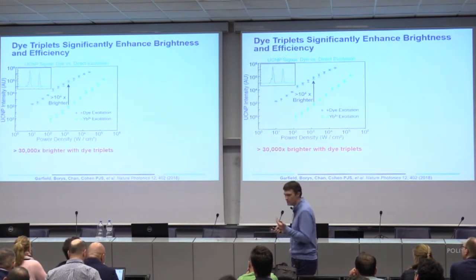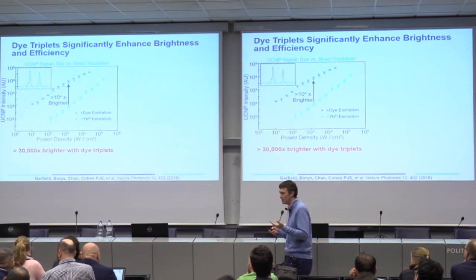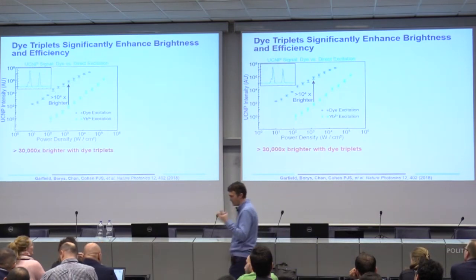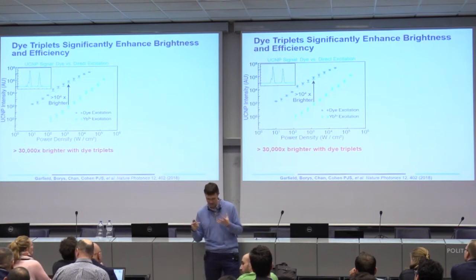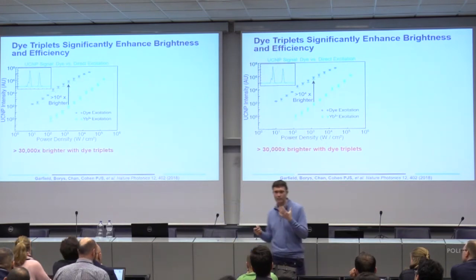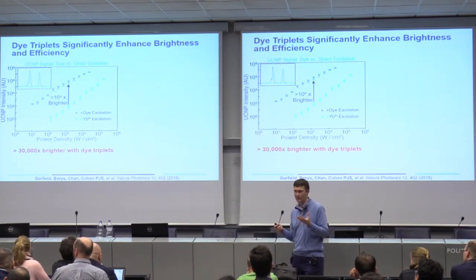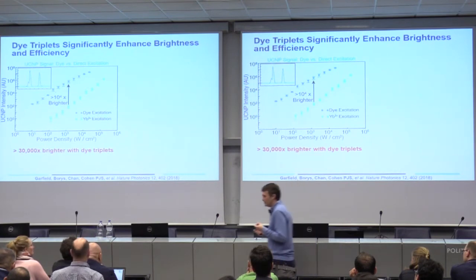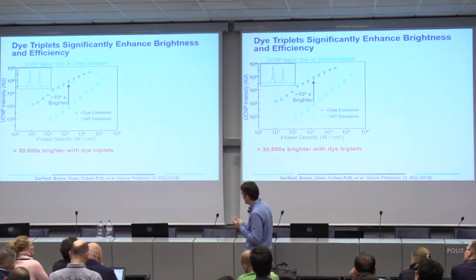And so what this means now is we put dyes on our molecule. We changed the composition a little bit so we could really take advantage of this triplet effect, this intersystem crossing. And now we have particles that are 30,000 times brighter than without the dyes. So this got us pretty excited. So yeah, 30,000 times brighter.